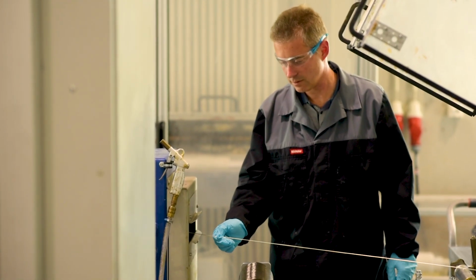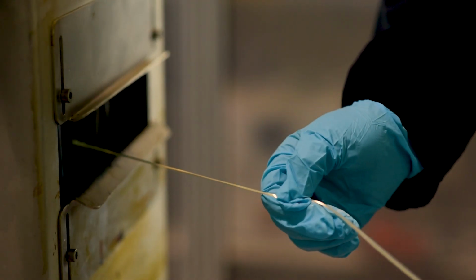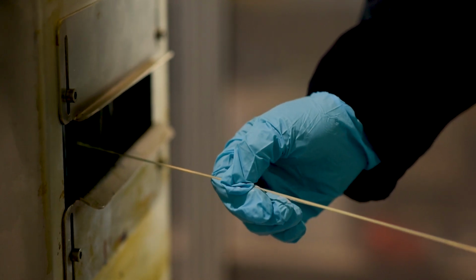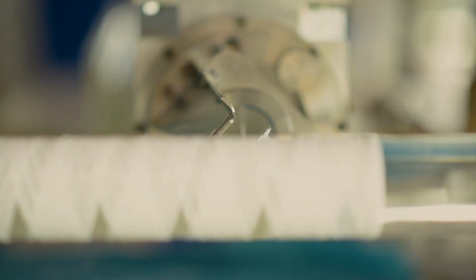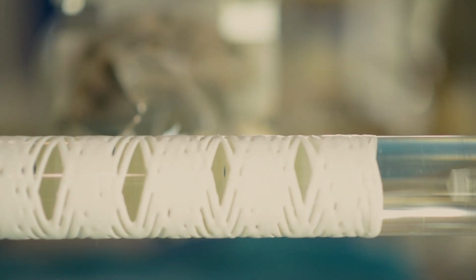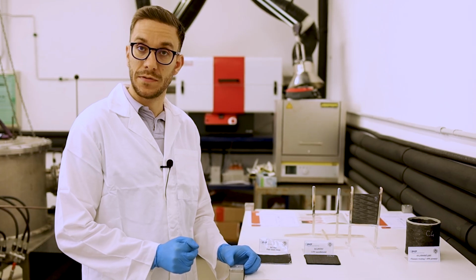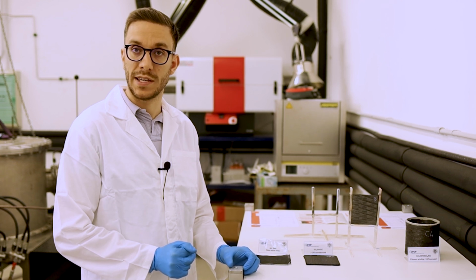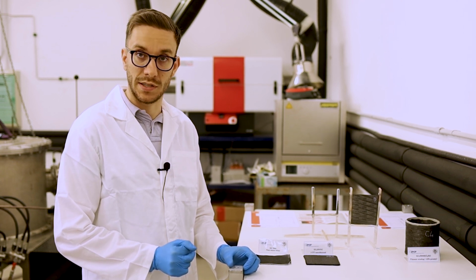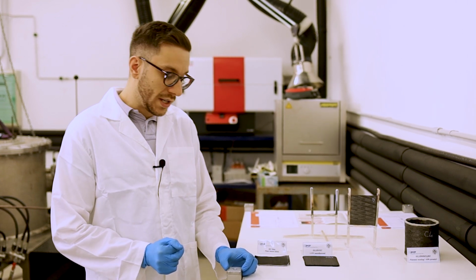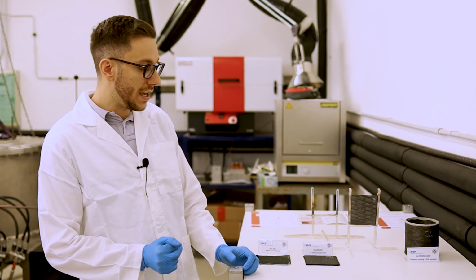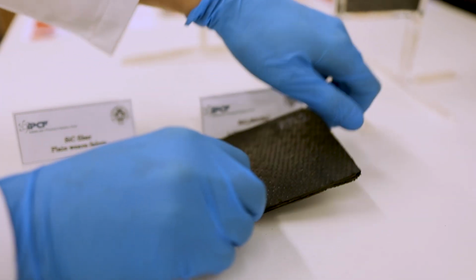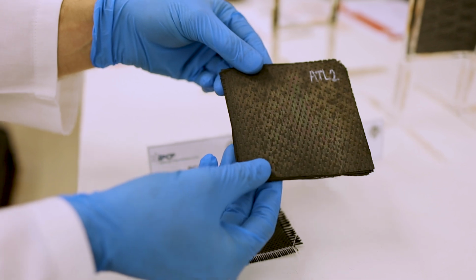Several challenges have been successfully tackled along the project, which first step dealt with the development of CMC's preforms, reinforced with coated fibers. Handling of ceramic fibers is quite challenging due to the fact that ceramic fibers are very stiff, and they become even stiffer once the interface coating is deposited on them. So we need specific routes to be able to achieve stable ceramic composites preforms.